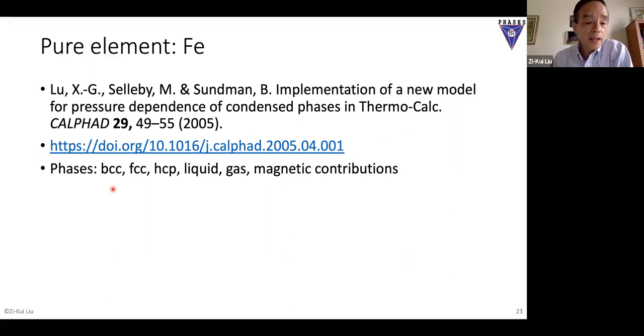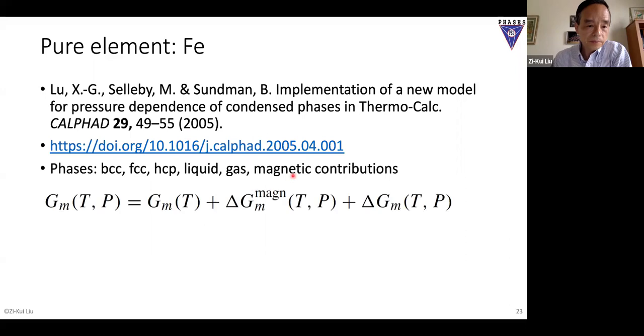However, at high pressure, you have the HCP phase. And also we know BCC is magnetic, so you can make contributions. So this is a typical model: the energy of a phase is a function of temperature and pressure. So you have a temperature component here. They have the temperature-pressure with magnetic contribution. You have temperature-pressure due to volume expansion. That's a function of pressure, okay?